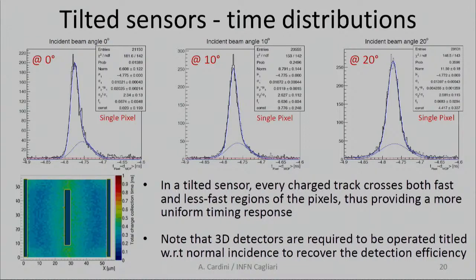So there's a small tail at normal incidence, and this tail goes underneath the main peak. This is due to the fact that the time response of the sensor is faster in this region of the pixel, but then it gets slower when all the charge carriers have to make the full crossing, even if they are electrons or holes. So the faster region is the central part.